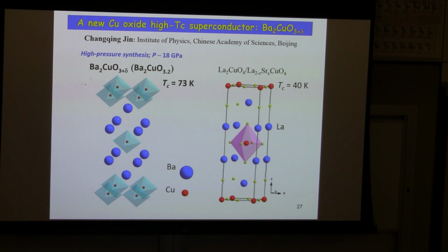What I'm going to introduce to you is that there appears to be quite a new type of cuprate that has a chemical formula something like this one. This is very simple. The material is composed of only three elements: barium, copper, and oxygen. Basically, the structure looks quite similar to the first Bednorz-Müller cuprate. It's basically the 214 structure, but you may notice there are some differences. In the case of the Bednorz-Müller material, the apical oxygen distance is elongated. On the other hand, this compound, the new cuprate, has a very compressed octahedron.